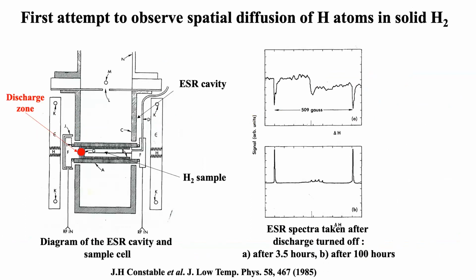This is the ESR cavity, the most sensitive part of this cavity is in the center. They made a sample of molecular hydrogen in the center of this ESR cavity and started discharge on the side of this sample. They ran discharge for a few hours, and after 4 hours they saw the signal from hydrogen atom. This doublet is characteristic of hydrogen atom. When they waited 100 hours, the signal became larger. So they proved there is spatial diffusion, but they didn't calibrate their spectrometer, and there is no quantitative information about how fast or how slow it is.